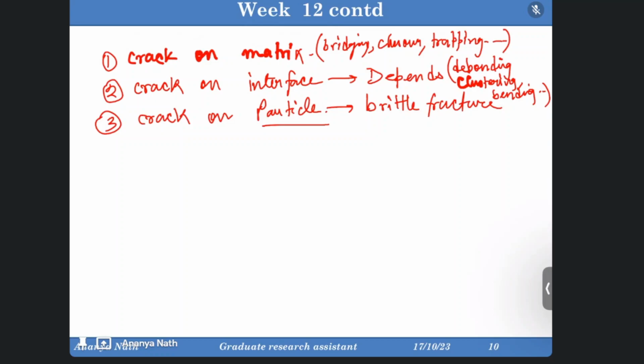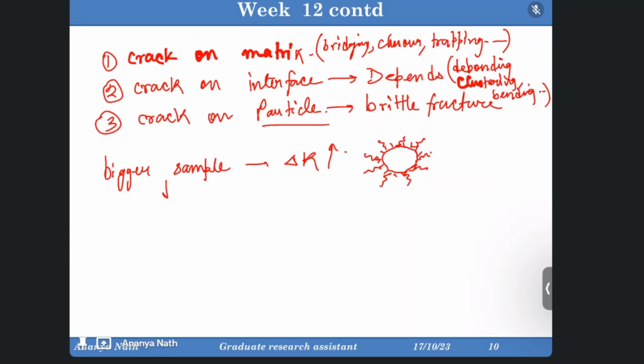Then in case of a bigger sample, the stress intensity factor will be more. This is the del K. Because the surface area which is embedded in the matrix is more, obviously the stress intensity factor will be more. This is the stress which is getting generated or gathered over here, so those are more prone to fracture. Bigger particles are always prone to fracture, and if fracture happens, then the number of interfaces will increase. It will enhance the chances of crack initiation.